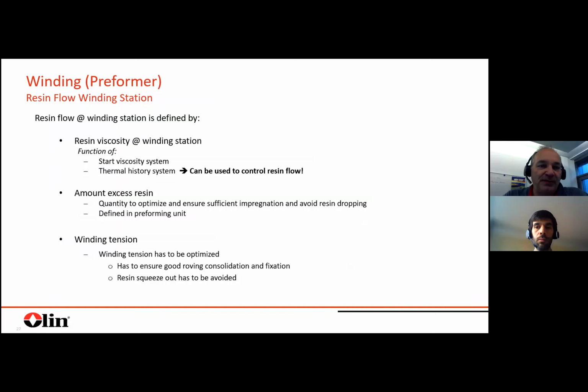So in terms of requirements, the critical part is here, if you wind it and, for example, the viscosity is too low, then there's a risk that you squeeze it out, that there's a kind of deformation of your profile. So that means that here the resin viscosity at the winding station is quite interesting. It's a function of the start viscosity for sure, but also the thermal history. So that means, have you preheated the bath? Is there some infrared heater for the fiber spreading? Have you a heating system in front of the preforming unit? So it means, is there any temperature or energy which pre-ages the resin before the winding station? Often, in most cases, not too much, so that is not a big effect, but it can also be used to, let's say, overcome issues if this is something which is recognized in the process development.